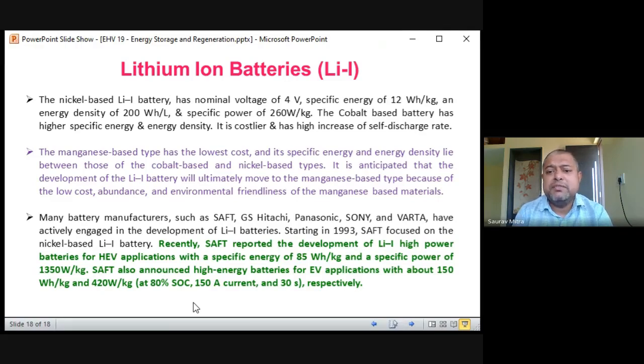Specific energy of 12 watt hour per kg and energy density of 200 watt hour per liter. I think this 12 watt hour per kg, I'll just check, maybe 120. A specific power of 260 watt per kg. So the cobalt based battery has higher specific energy and energy density. It is costlier and has an increased self discharge rate. So self discharge in this case is little higher.